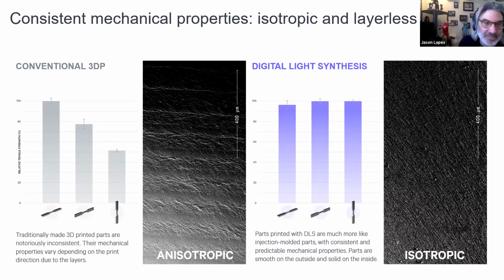So a little bit more of a close-up of an actual part that we'll see comes out of the acceleration station today. If you look on the left-hand side, with conventional 3D printing, orientation matters. How you orientate will only give you the best result in one direction for strength. Anywhere else you orientate will produce a weaker part. And if you look at the first image of the 400 micron close-up, you'll actually see those layer lines inside of the part. Those are actually weak spots in the part that could give you a susceptible part failure out in the field.